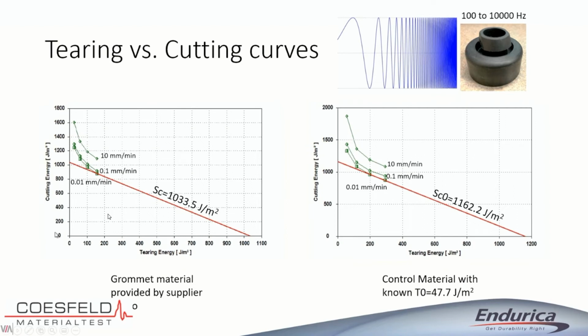The y-axis is an additional contribution to the tearing energy that is coming from the blade, right? So I mentioned that we instrument the blade, so we're measuring the forces, and if we know the forces, we can calculate the tearing energy that's due only to the blade. And what we do is we construct this plot of cutting energy versus tearing energy, and you can see I've plotted these for the three different rates. And what you see is that at the high rate, you're measuring higher energies. As you slow the measurement down, the curve kind of converges. And really what you're trying to estimate is what would be that curve under conditions of basically very slow crack growth.